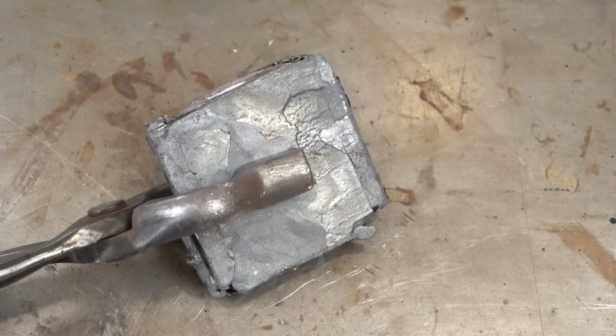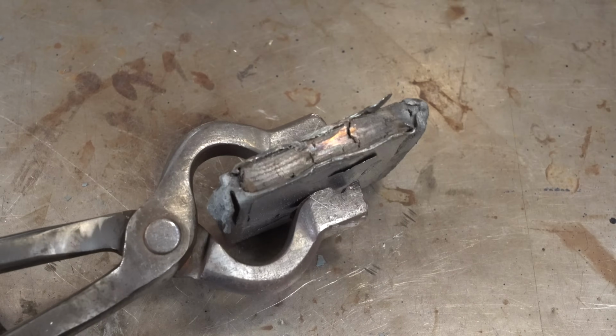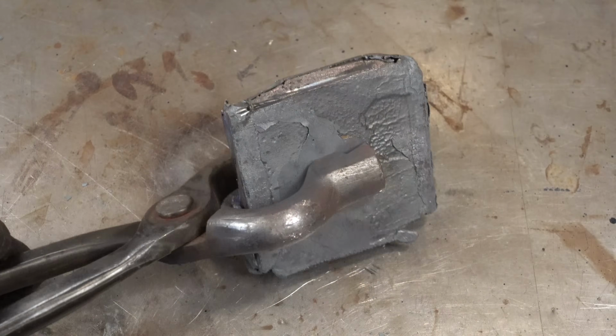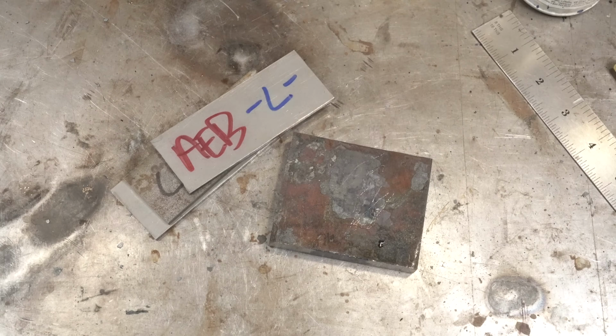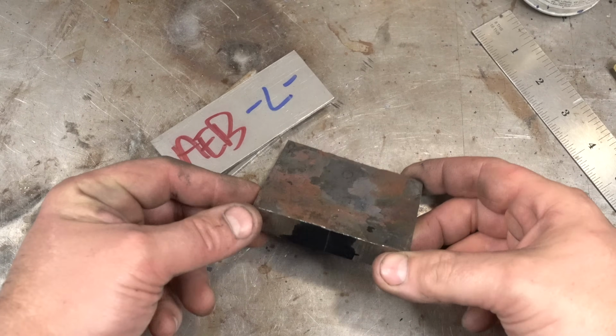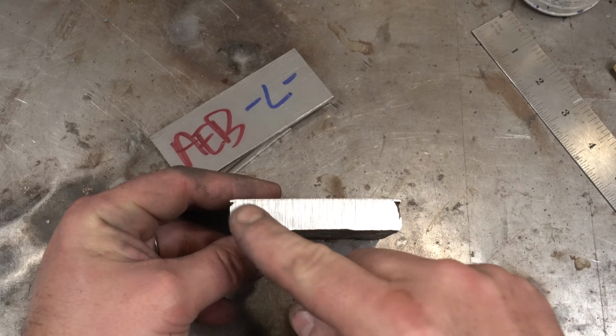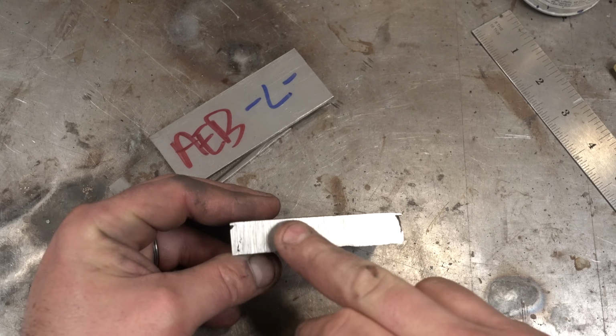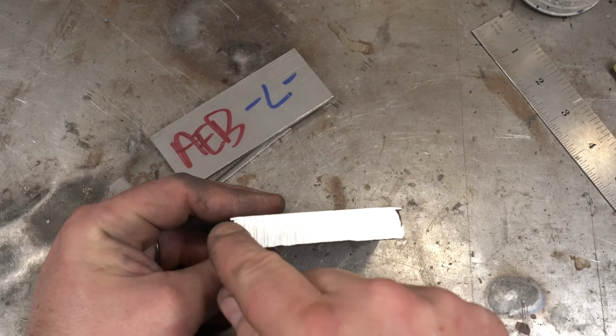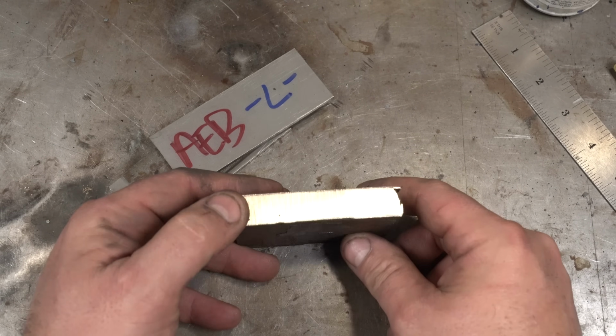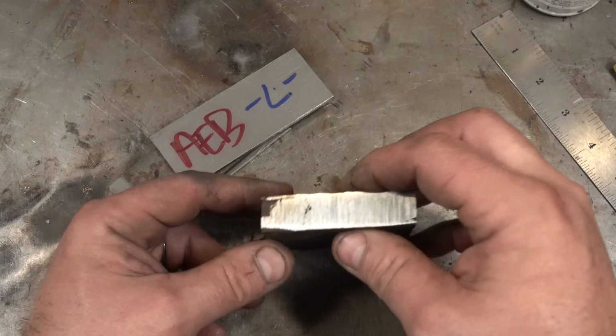Now this has got to go in the oven for another anneal session for 4 hours before we do any grinding or anything else on it. So here is the results of my second weld. The weld itself is flawless. I don't see any issues. There's a little crack here, but I just haven't ground into it enough.